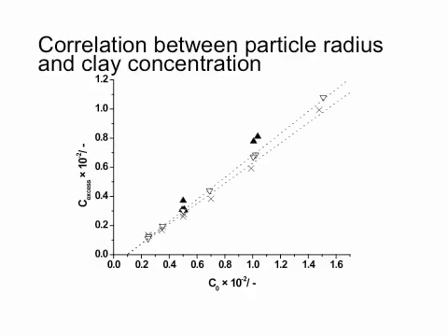So if you plot the amount of clay that you put in, and you calculate CXS with the equation that was given on the previous slide, what you'll see is that a lot of these experiments fall quite nicely on the two dotted lines. The two dotted lines are two series of experiments: in one case we added 4 weight % of hexadecane to the droplets of styrene, and in the other case 8 weight % of hexadecane.